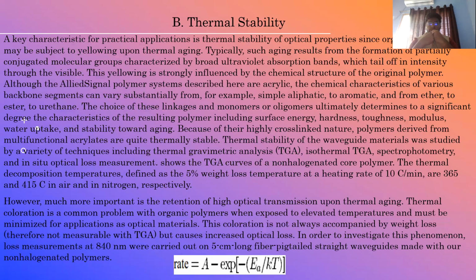The thermal decomposition temperatures, defined as the 5% weight loss temperature at a heating rate of 10 degrees centigrade per minute, are 365 and 415 centigrade in air and in nitrogen, respectively. However, much more important is the retention of high optical transmission upon thermal aging.